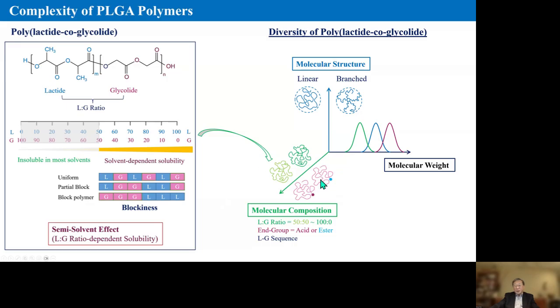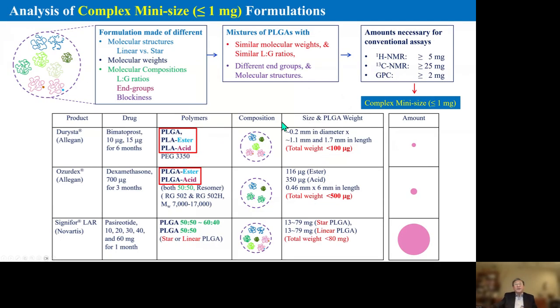So molecular composition is one of the important parameters that control the PLGA behavior, also molecular weight, and the other parameters are molecular structures. Linear structures versus branched structures, the main difference is the viscosity, even if they use the same concentration of PLGA. So today, let's assume that a formulation intentionally has two different molecular structures, different molecular compositions, and different molecular weights. If all those three different composition parameters are in the same formulation, furthermore, if the total amount of PLGA in terms of weight is less than 1 milligram, then we have a serious challenge here, because for using conventional assay methods, we need more than a milligram quantity for individual assays. So having less than 1 milligram poses serious challenges.